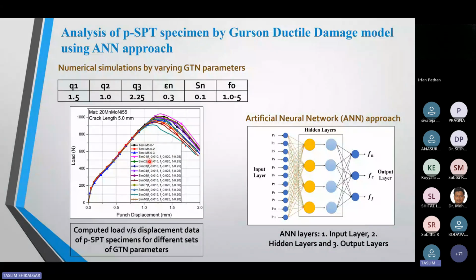And after training these artificial neural networks, I provided the experimental load data at the same punch displacement to the neural network. After providing the experimental data, I got FN, FC, FF as an output. And this is a good way to obtain damage parameters for any experimental data. So I used this methodology to obtain the damage parameters for my material.